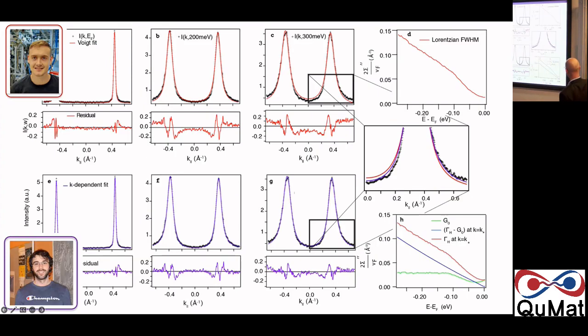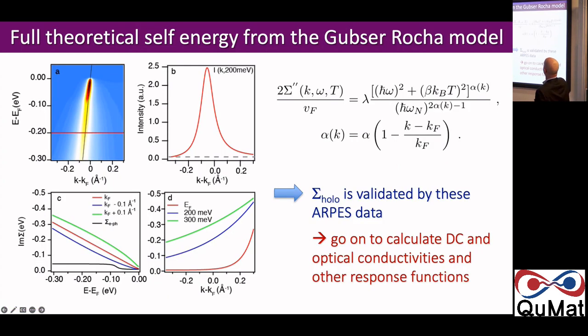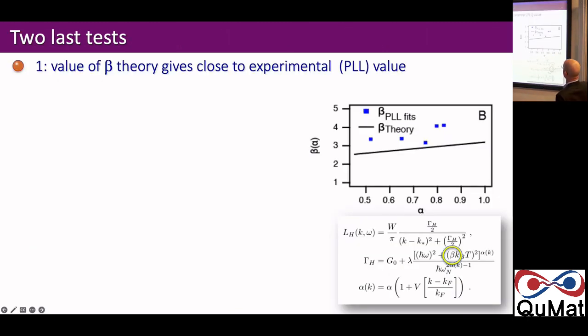So we have the self-energy, the electronic one, optimal doping, that's this guy. We have the electron-phonon interaction that we've modeled as this green one. You add them together, you get the experimental. In fact, this is the experimental self-energy minus the electronic one, gives you this green curve, and it looks exactly like a step at the phonon frequency. Okay, so there is this full theoretical self-energy, and now it's people's job to go away and use it, because it's been experimentally validated. So 2 last tests.